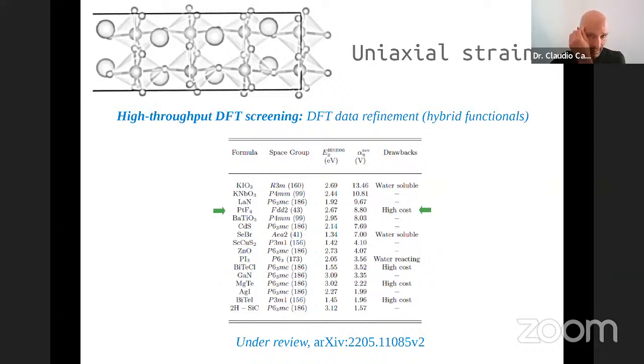Then also these halides, so lead fluoride. It's quite good in terms of band alignment tunability, but probably it's not ideal in terms of cost. On the other hand, our final screening identified barium titanate and zinc oxide, which are the two archetypal piezo photocatalytic materials. So this is a good thing. And actually they are quite well positioned in this list.